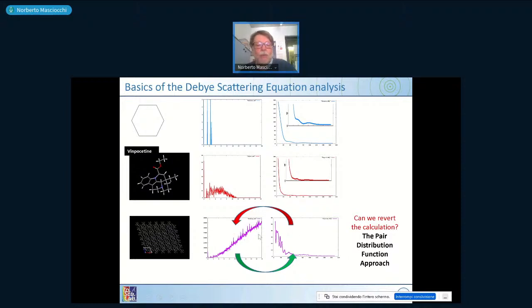Unfortunately, this is not what we normally measure. We measure the scattering pattern, and we would like not to compute the scattering pattern from a model, but to retrieve the model, the red line, from the scattering pattern. This is called the pair distribution function approach, which tries to obtain this information from experimental data, here on the right. As you can imagine, the details of this information are very tiny, so it is very difficult to obtain. While the one-way direction, which is to build a model and compute the pattern, is much more straightforward.